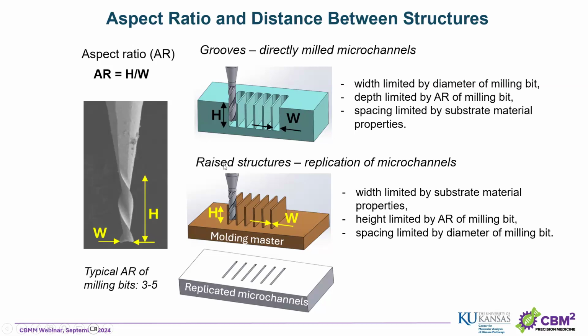And on the other hand, if we're using the second approach, when we first manufacture the molding master and then replicate it in the plastic, the limits on structures are a little bit different, because at this time the spacing between structures is limited by the size of our bit. But at the same time, the structures of the replication can be much narrower than in direct writing. So they're not really limited by the bit size. And I'll show you some pictures in a minute.